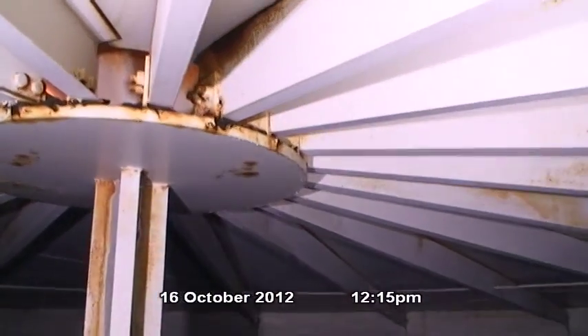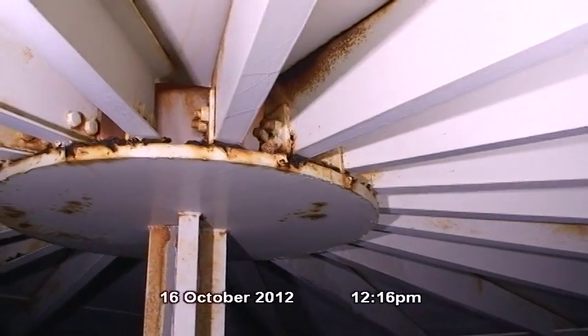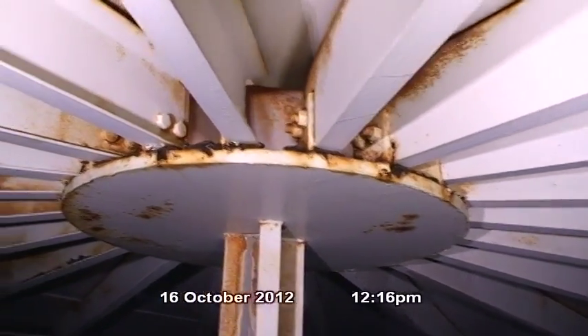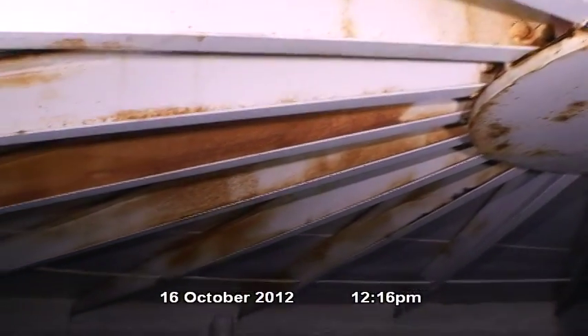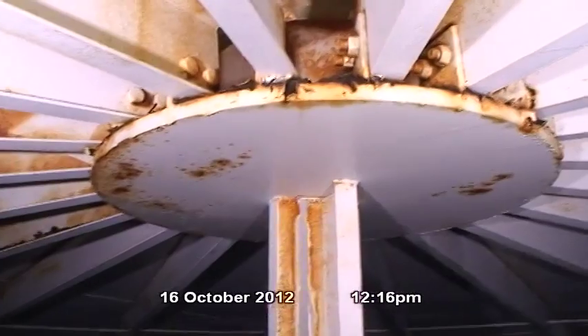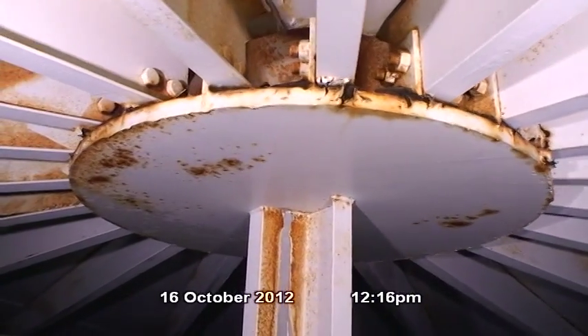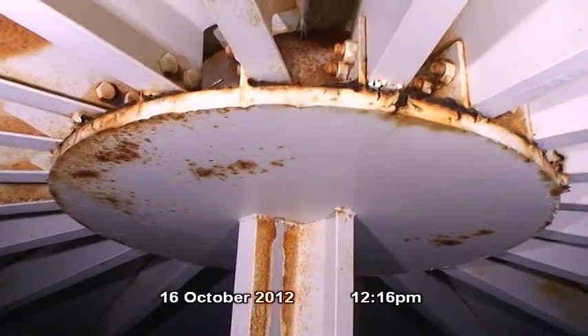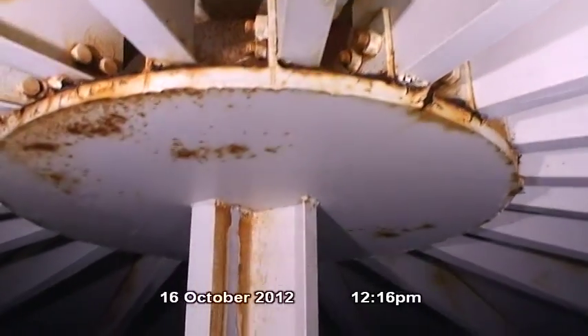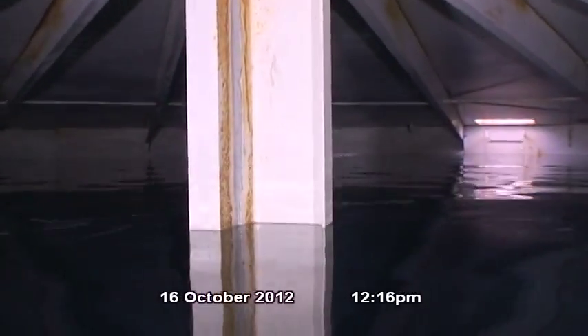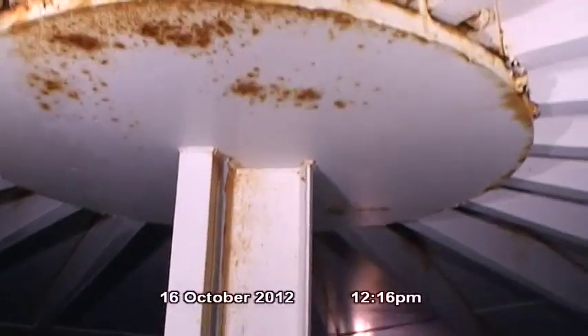Light surface corrosion is present on the center pole above the waterline. The hat plate is coated with epoxy. Concentrated areas of light surface corrosion are present on rafters near the hat plate. The coating on the hat plate appears to be losing flexibility, cracking and delaminating in a few areas where rafters are bolted to the hat plate. Moderate to possibly dense corrosion and metal loss is taking place in a few areas on the hat plate.